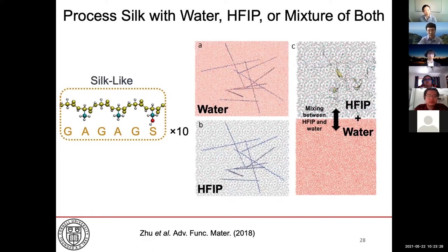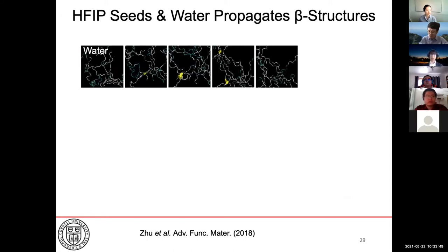Now, using multiple strands of silk-like peptides that I've generated and is generalized by this GAGAGS sequence, I solvated them in water, or I solvated them in HFIP followed by mixing with water. And here we look at snapshots of five different classes of silk after processing. Solvation in only water induced hydrophobic aggregation, right? And this is expected because that's how silk would react in water, right?